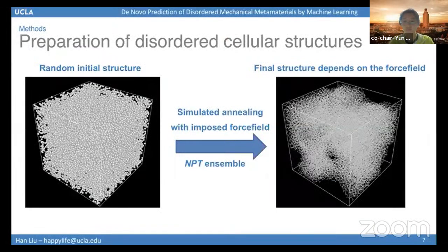Given an underlying force field, I prepared disordered structures using molecular dynamics simulations. That is, starting from a random initial structure, I conduct simulated annealing with the imposed force field and the NPT ensemble. The final structure is a disordered porous network governed by the force field.